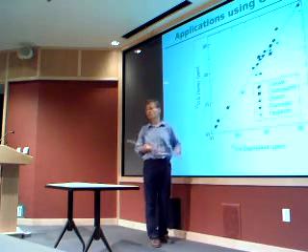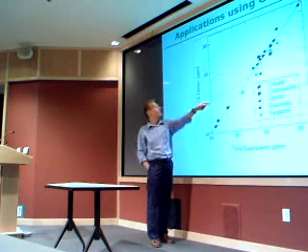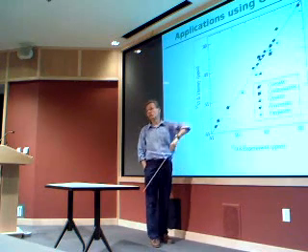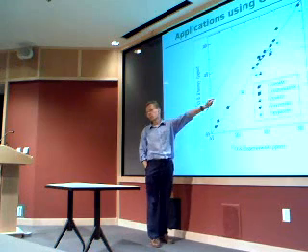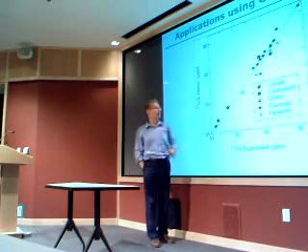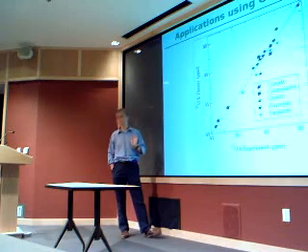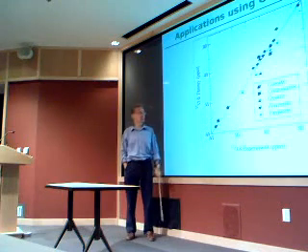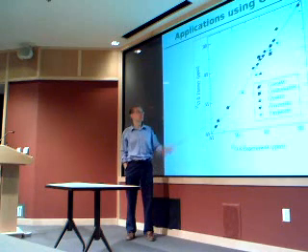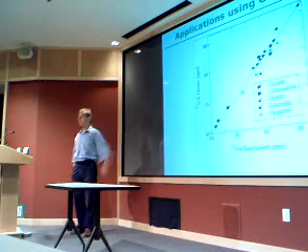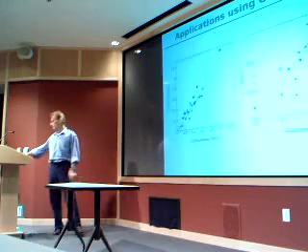They're not exactly there, but the difference is quite small. There are some 4 or 5 ppm errors, but they are more on the diagonal. So qualitatively, you have everything well in place. Silica is quite an easy material in a sense, but the remaining errors, is it the exchange correlation functional, or is it some numerical things? That remains to be seen, but this is what you can expect for the accuracy.